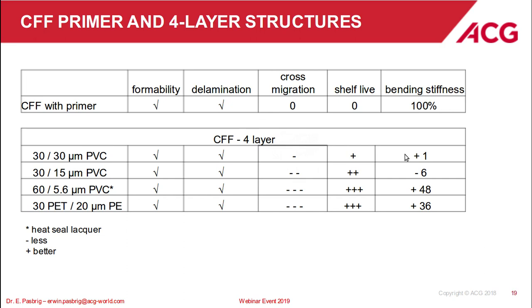The bending stiffness of this material, in the case of 30 and 15 micrometer PVC, is more or less the same like standard material. On the outer side, a thicker layer of PVC is applied when bending stiffness is increasing. The same as polyester coming onto the laminate with polyethylene.